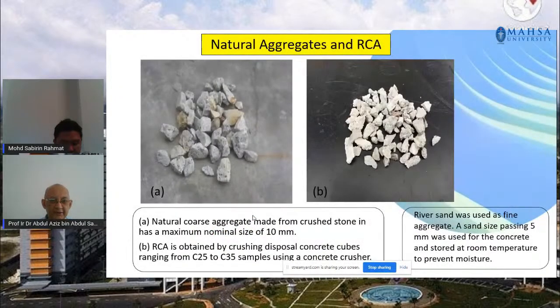And this is the aggregates and the RCA that we will be using in our mix. The one on the left hand side is the normal aggregates, whereas the one on the right hand side is the recycled concrete aggregates that we produce in the lab. And the sand that we use in the mix is river sand, passing 5 millimeters. The size of the material is roughly about 5 millimeters.